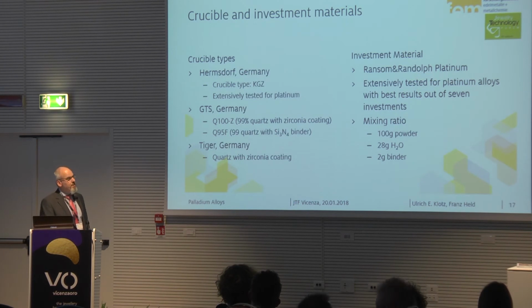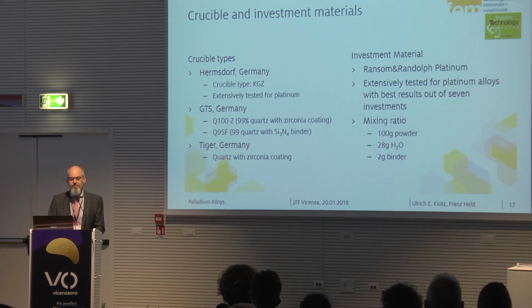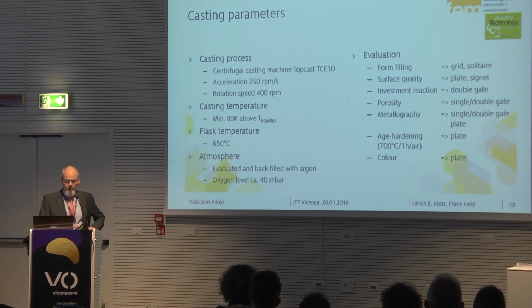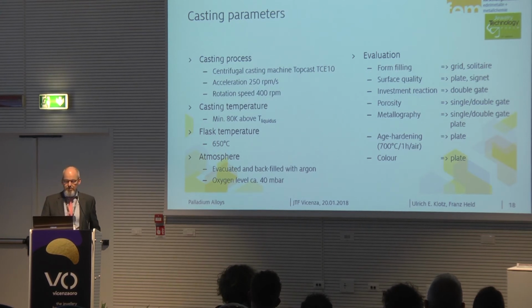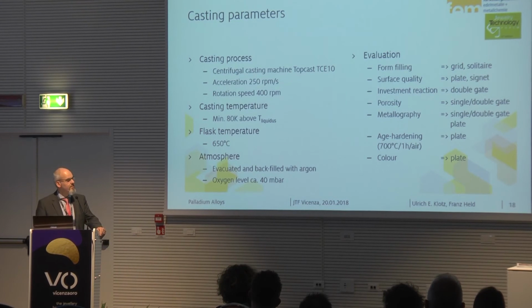These are some parameters of crucible materials and investment materials. This is more or less the standard selection that is also used for the casting of 950 platinum alloys. In our casting process, we use a centrifugal casting machine with these parameters. We overheated the melt to minimum 80 Kelvin over the melting temperature, and our flask temperature was set to 650 degrees, which was an established value for platinum alloys with such a setup.